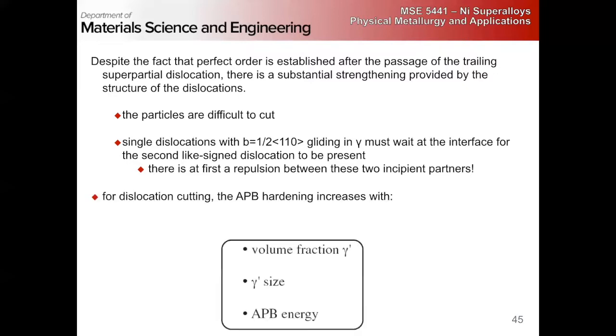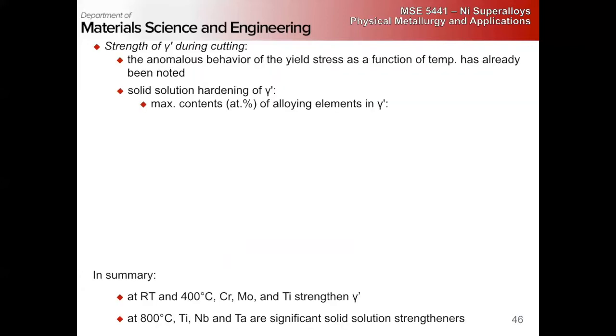The same types of reactions become even more complicated when you take partials into account. A lot of the mechanisms involve local reordering to reduce fault energy. So you have to have Shockley partials of the right type, either on the same plane or separated by one lattice plane. So there's a significant chance and time effect to get the right dislocations to cut through the gamma prime particles, because otherwise the energy cost is just too high.